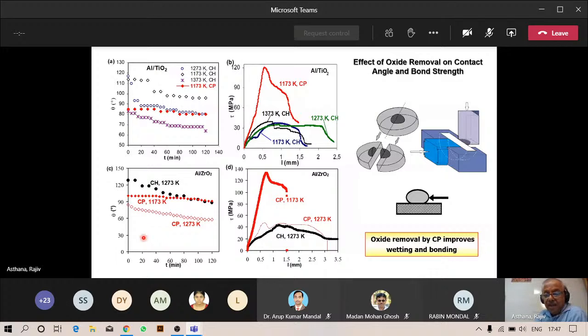In wettable system, the liquid can spread out quite a bit. So pushing the droplet sideways is not very helpful, especially if the droplet is very thin. So we use this bisectioning approach. We would bisect the droplet substrate combination after cooling, and then use the shear test to slide off one half of the droplet.